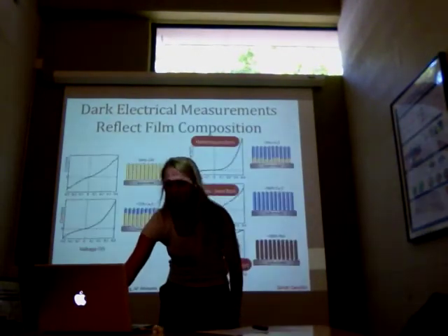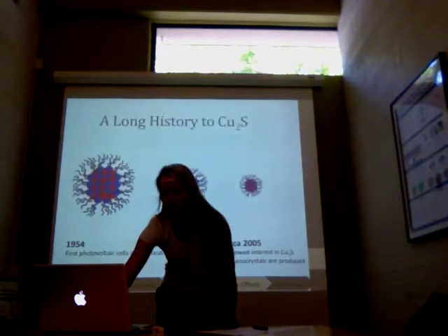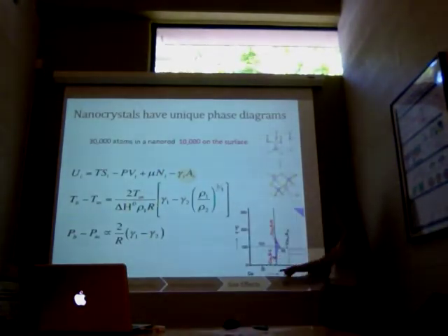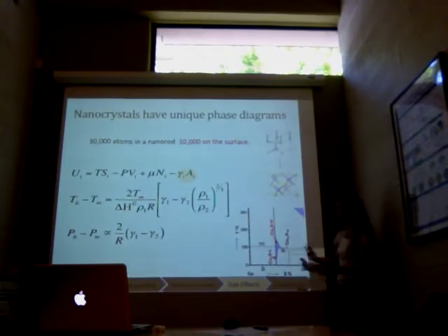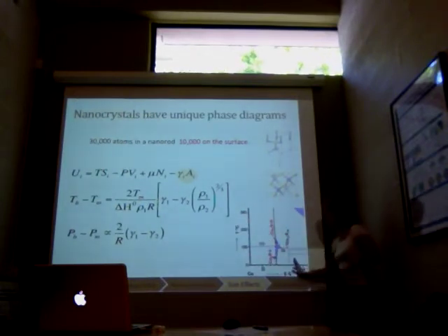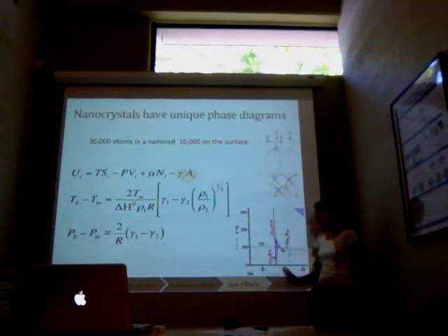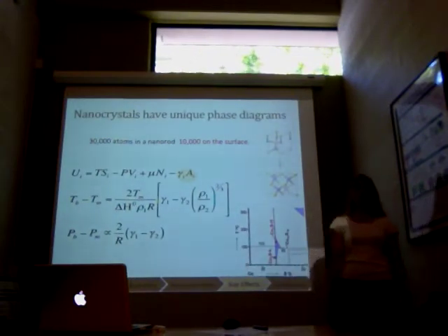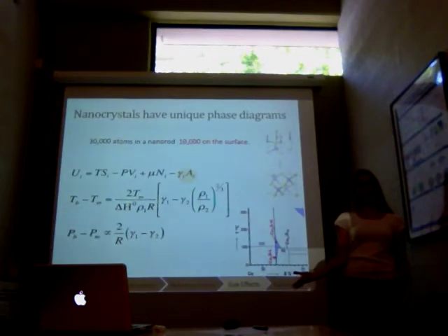So there have been reports in the literature. I see, but it's hard to isolate that. Well, this doesn't show the whole space. This is very narrow. But as you move around, you've got this very complex phase diagram as you change your stoichiometry and become copper deficient. And people have a very difficult time measuring whether or not they're actually stoichiometric or if they're 3% deficient, which makes the properties dramatically different.